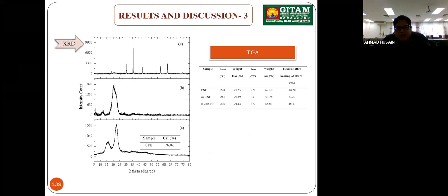The result for the XRD shows that for the CNF the crystallinity index is 76%, and the structure is a cellulose type I representation, similar to the native plant. For the carboxymethyl nanocellulose, the combination of these two peaks diminished and formed another type of peak, which represents more of an amorphous type. For the introduction of the ferrum oxide, 6 new ferrum oxide peaks were observed, contributing to the crystal planes from the iron oxide, and it diminished all the planes from the cellulose.